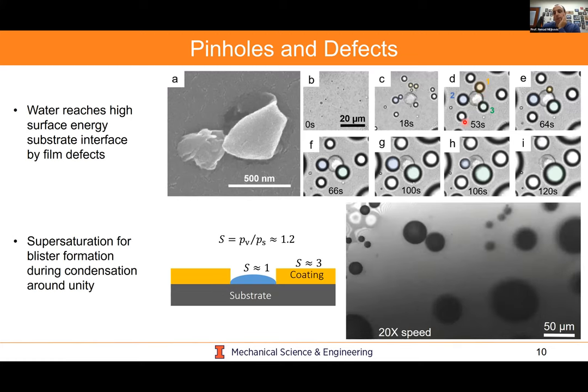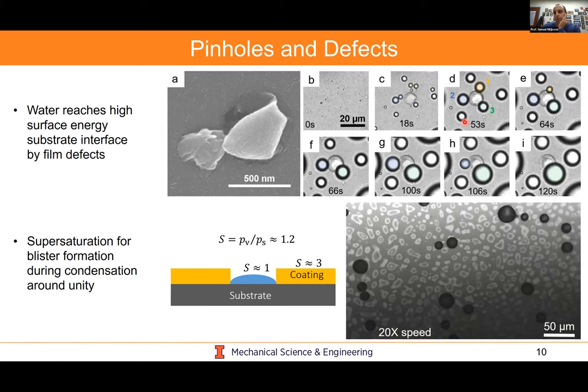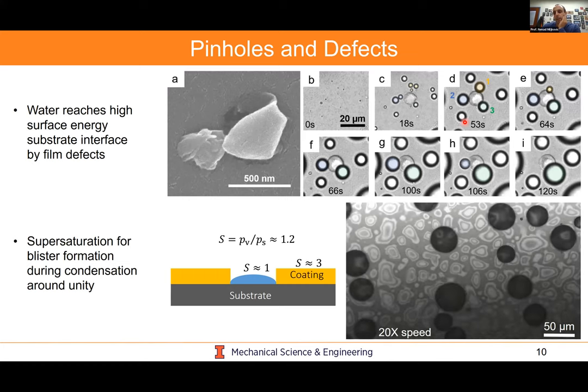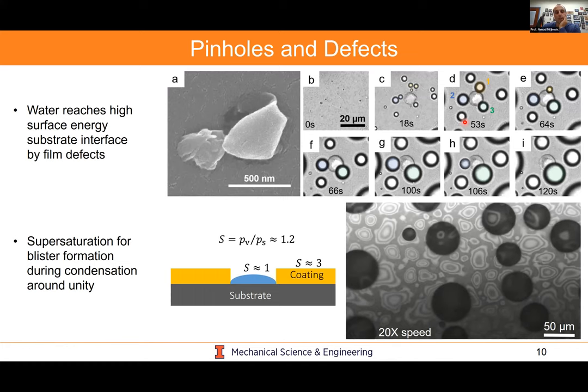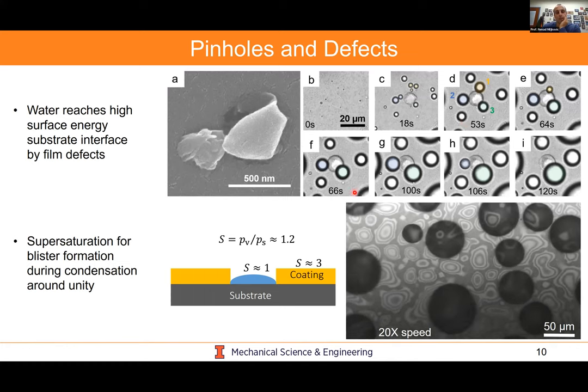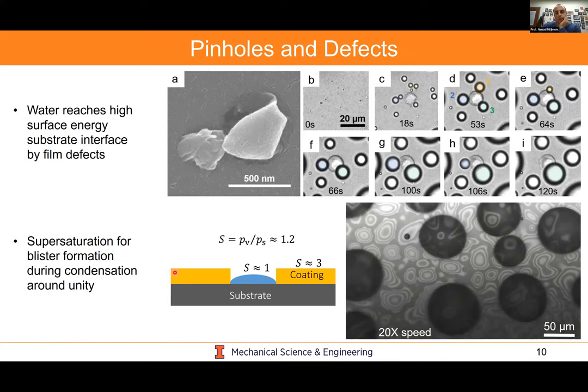So this was a first insight, proof that these blisters were water-filled, and it gave us some insight into the presence of pinholes on the blister itself. What these pinholes end up doing is exposing the substrate surface for condensation.